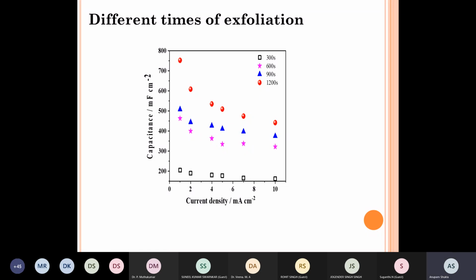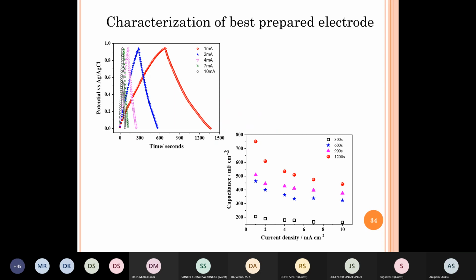With this, we therefore did this partial exfoliation in 0.1 molar sulfuric acid, but looked at the time of exfoliation, and we found that 1200 seconds gave better results. Of course, with the current density we were using, we could not go beyond 1200 seconds, because after that, enough of the material has detached from the electrode that it did not have the required mechanical strength. These are some of the characterization of the best prepared electrode.